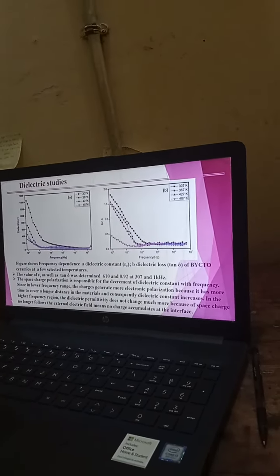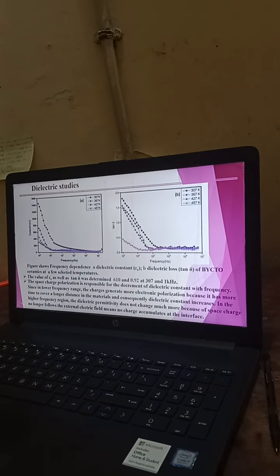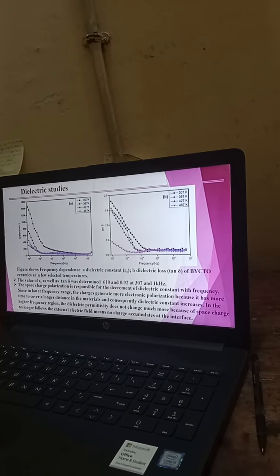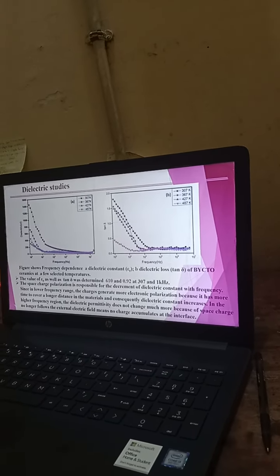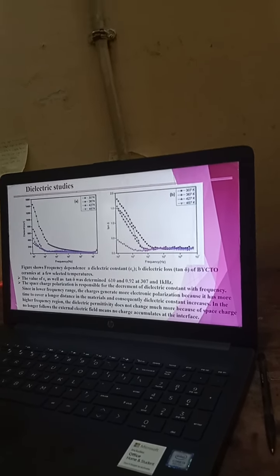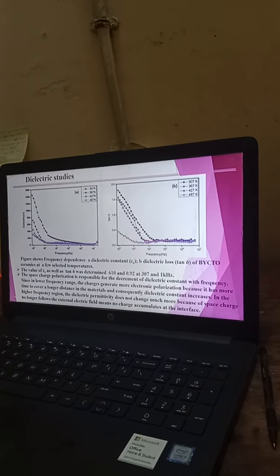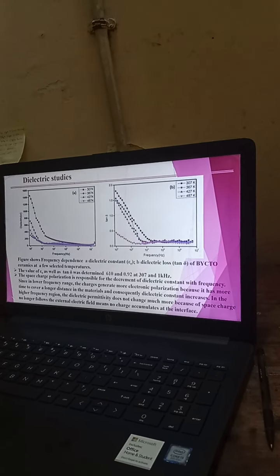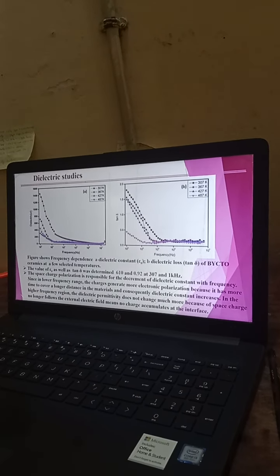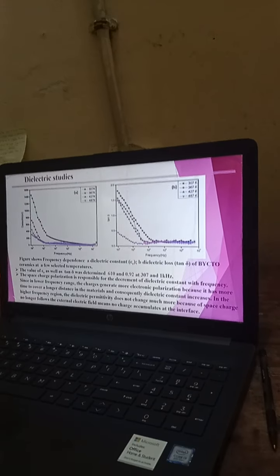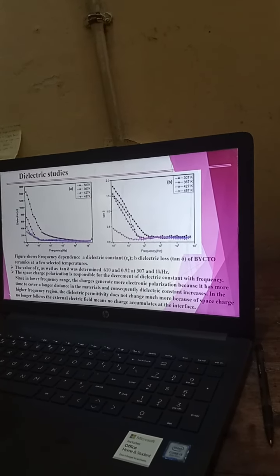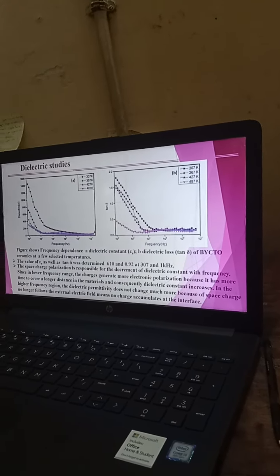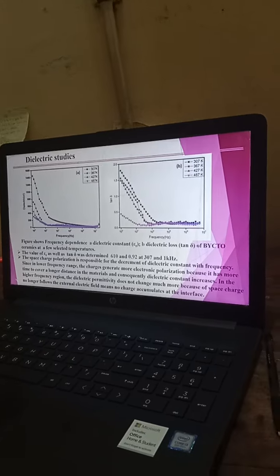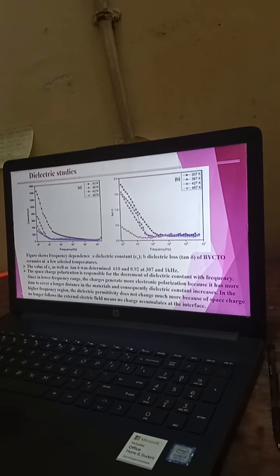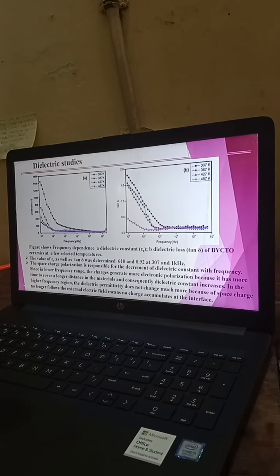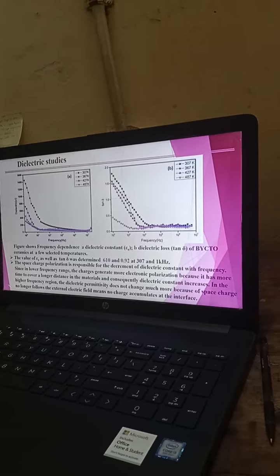Dielectric studies of the BYCTO series. Figure A and Figure B represent the frequency-dependent dielectric constant and dielectric loss of BYCTO ceramic sintered at 900 degrees centigrade for 8 hours at different temperatures. In this figure, we have observed the dielectric constant decreases with increasing frequency and is almost constant after 10 kilohertz. The decrement of the dielectric constant in the lower frequency region, as well as the dielectric loss, is due to space charge polarization.